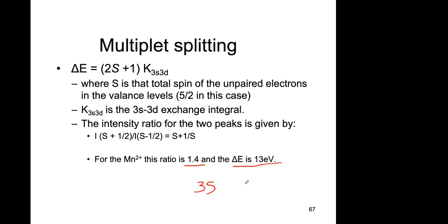So meaning that if you have the 3s electron level where you have two spins, minus 1/2 and plus 1/2, it's not the same. The binding energy of removing this electron is different than the binding energy of this electron. They are not the same. And that's impressive. It's because the final state that you achieve has a different total spin, and that affects how easy or less easy it is to remove an electron with a certain spin.